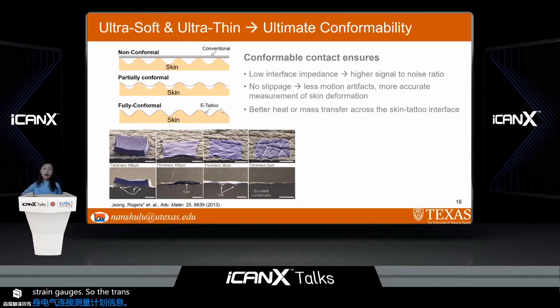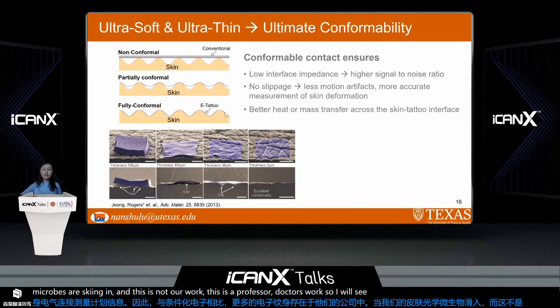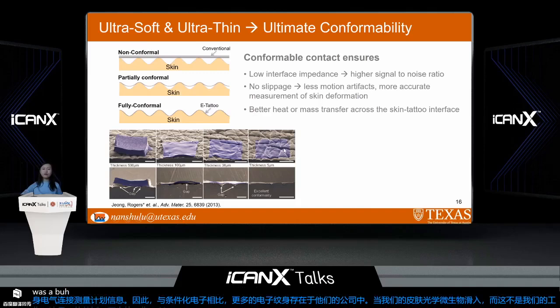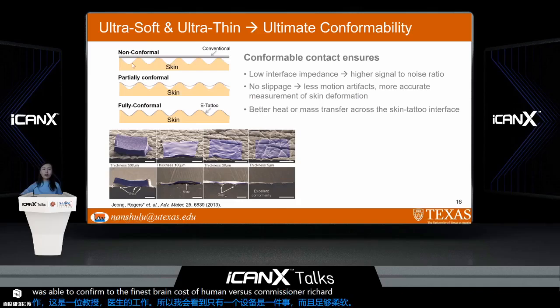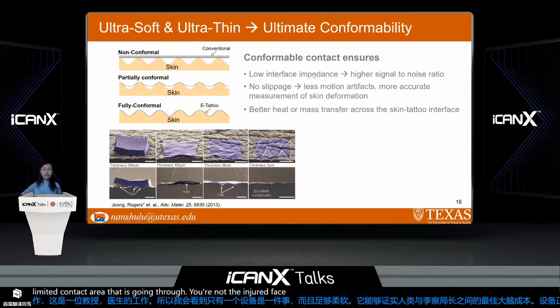The intrinsic merit of electronic tattoos compared with conventional rigid electronics lies in their coupling with our skin. Under optical microscope, our skin is rough, and this is not our work. This is from Professor Rogers' work. So we can see that only when the device is thin and soft enough, it is able to conform to the finest wrinkles of human skin, versus conventional rigid devices sitting on our skin like a rigid board with very limited contact area. That is going to limit the interface impedance to a high level, and that can lead to a very low signal to noise ratio.